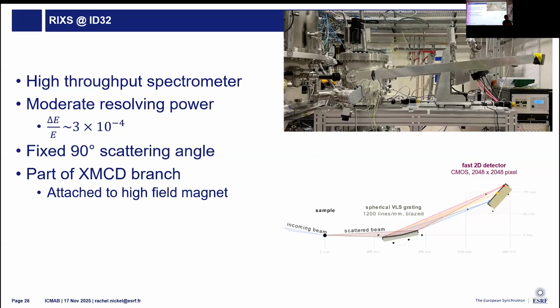It has a fixed scattering angle, so we cannot do the full momentum space maps, but it's within our magnet. And this gives the unique possibility of doing high field MCD or MLD RIXS. So if you have a magnetic material and you want to separate out what the excitations are, the dichroism of the different sites, the individual energy levels, we can do that at this branch. And this is a novel capability at ID32. We also have the option of a lower base temperature and a few more tricks in terms of sample environment that we can do here.